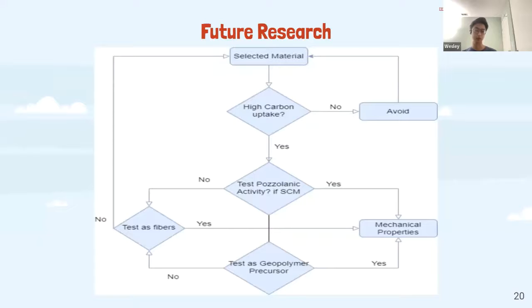And assuming it has high pozzolanic activity, we would also test their mechanical properties, so the effects that the SCM has on concrete. And then lastly, there's geopolymer concrete, which is essentially a full replacement of cement, like a 100% weight replacement. This would be the ideal situation because you would replace all of the cement, which is where the majority of carbon emissions from the cement industry comes from. So we would test if it has any potential in fully replacing cement, which is our final and last step. But yeah, next slide.